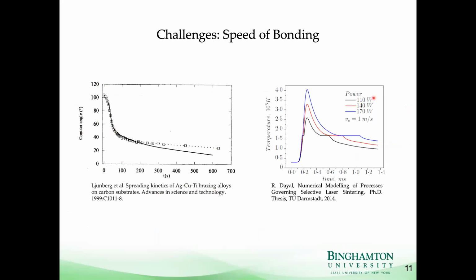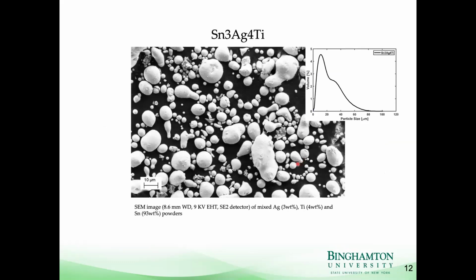So can we really create a good bond in that small time that each pixel is heated up? So we mixed up tin silver titanium powder, and we've tried a few different processes for doing this, but this is a heterogeneous mixture. We bought tin silver and titanium and mixed it here. We've also done ball milling to alloy the material, and both have worked. So now I'd like to show you a video of the print process.